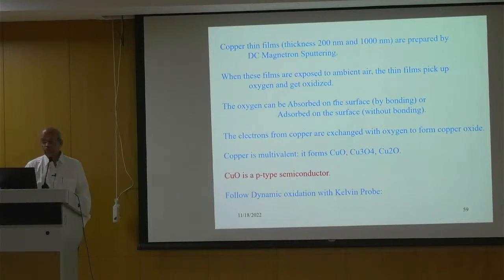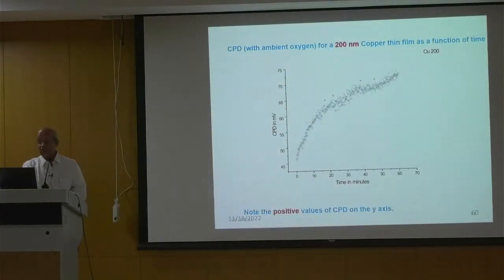And remember, CuO is a p-type semiconductor. P-type semiconductor means the Fermi level is very near to the valence band. You get a large contact potential difference. This is the contact potential difference we got. CPD is positive for 200 nanometer copper thin films, and as a function of time t, we used to follow the oxidation process in this manner. After some time, it is going to get saturated. So it took about 60 to 70 minutes to get oxidized, because this is first order kinetics. In first order kinetics, initial oxidation is going to be much more rapid, afterward it slows down. And the important point is this is a positive CPD.